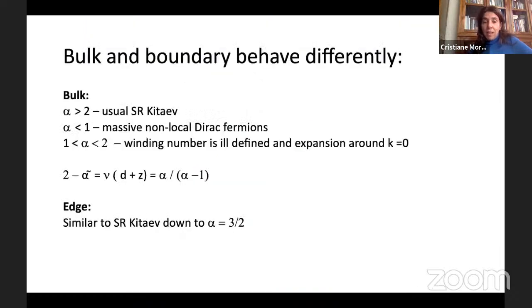Well, the bulk and boundary are also behaving differently here because of these long-range interactions. So for alpha larger than 2, I see the usual short-range Kitaev chain. For alpha smaller than 1, I get this massive non-local Dirac fermion because I started gapping my Majoranas. And for alpha between 1 and 2, I get this ill-defined winding number when I expand around k equals 0. And for the edge, it is similar to the short range down to 3/2.